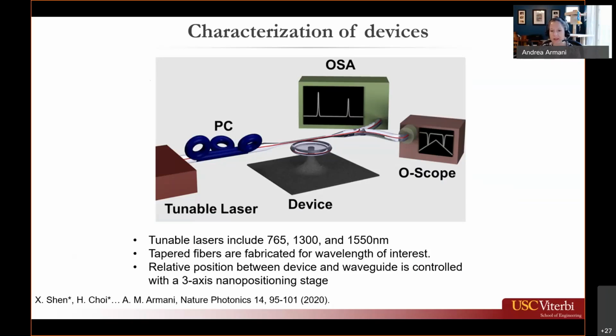Being able to simultaneously measure and monitor the quality factor and detect the spectrum is an important feature because it allows us to look for any kind of variation in Q during the measurement and confirm that our resonant wavelength isn't moving. And the coupling gap between the waveguide and the device is accurately positioned using a nano positioning stage so that we can maintain constant coupling.